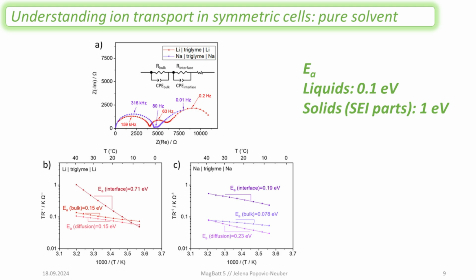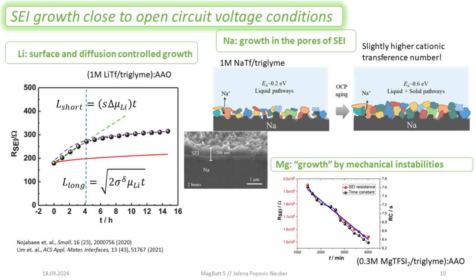So in the case of sodium, we actually can see that also with FIB-SEM. These SEIs form very quickly, and we can even see that this porosity is quite big. It's hundreds of nanometers of pores. But in the case of lithium, it is not very easy to see it, and the contribution of the liquid pathways is much smaller than in the case of sodium. So in my opinion, this is the reason why we have never thought that this could also actually be porous since the mid-90s.